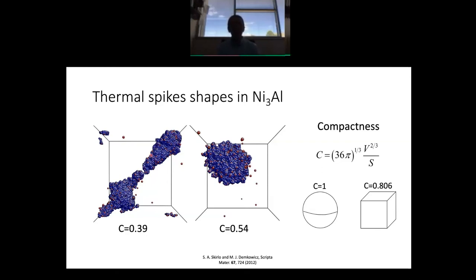So to figure it out, what we did is we characterized these thermal spikes. We characterized their shapes using a parameter called compactness. And compactness is basically like a volume to surface ratio. It basically takes the volume of the thermal spike, raises it to the power 2/3, divides it by the surface area of the thermal spike, and we can calculate all of that based on our simulations. There's a little normalizing factor here to make it so that the compactness of a sphere is 1, right? The sphere has the highest ratio of volume to surface area. So the compactness of a sphere is 1. Anything that has a higher surface to volume ratio than a sphere has a lower compactness. So for example, a unit cube has a compactness of 0.806, all right? And so for each of these thermal spikes, we could actually compute their compactness values.